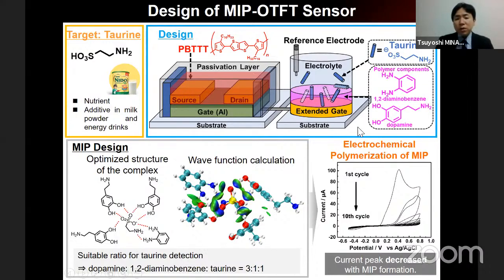1,2-diamino-benzene and dopamine. Before we fabricate the MIP, we designed it based on wave function calculation and DFT calculation. The calculations predicted that the component ratio of dopamine, 1,2-diamino-benzene, and taurine should be 3 to 1 to 1. In this ratio we can obtain the complementary complex. Based on such calculation, we mix these components and polymerize them by an electrochemical method.